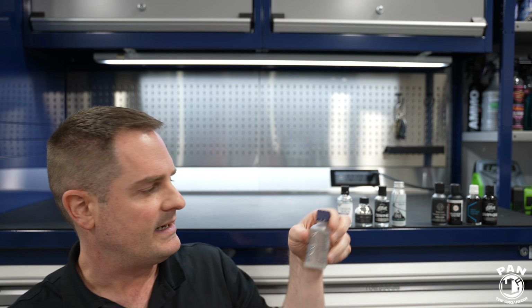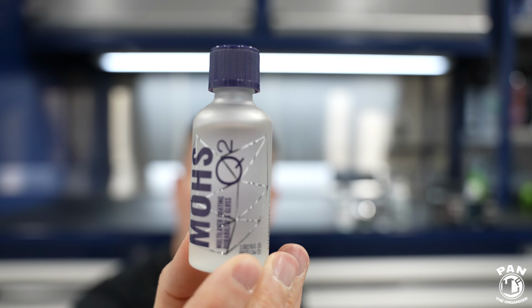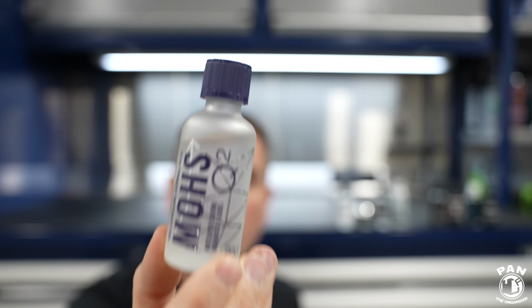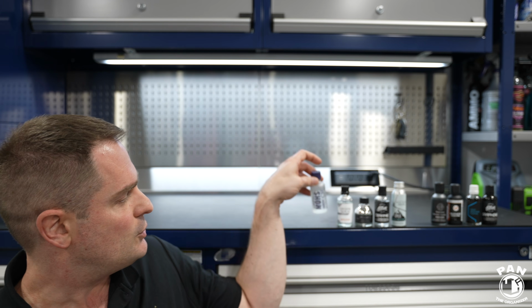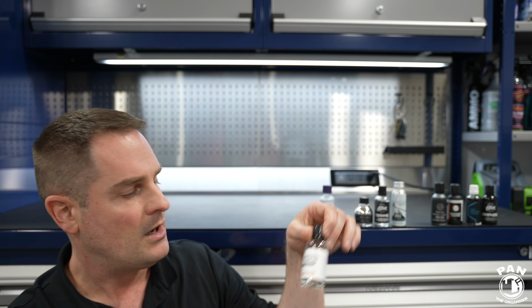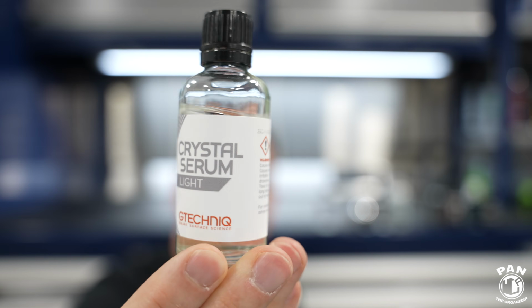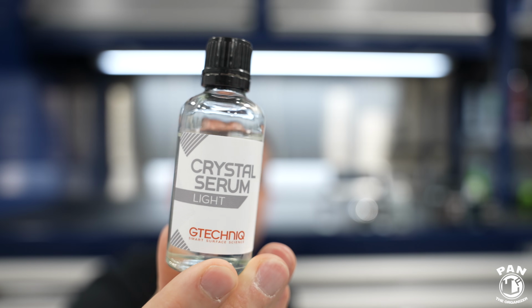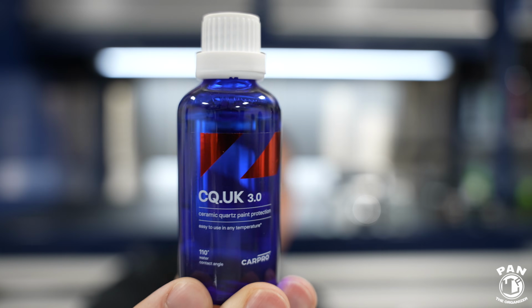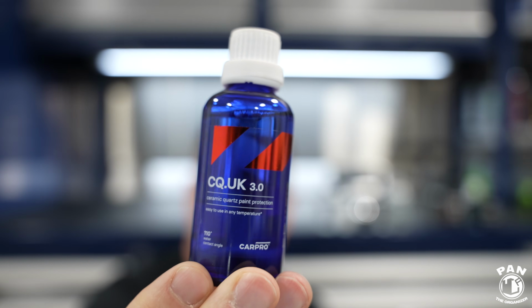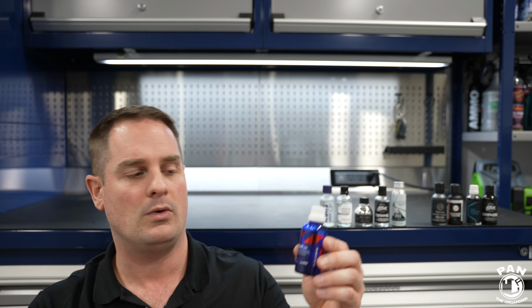Some coats, like MOHS, require, not recommend, require two coats to function properly, so you absolutely have to apply. Other coatings, like Crystal Serum Light, only require one coat of the base ceramic coating, and others like the CarPro C-Quartz UK 3.0 recommend two coats. So of course, try to follow the recommendations, and the times between coats have to be respected as well. The majority of coatings require 45 to 60 minutes between coats.